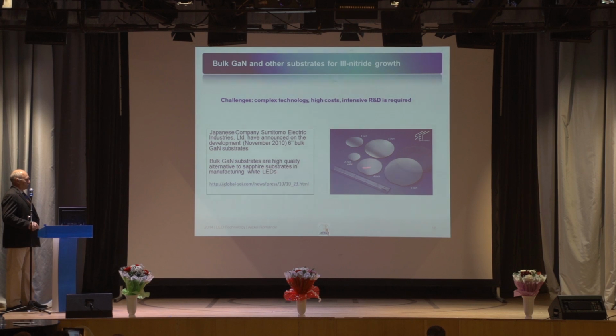And here, of course, there is a challenge to get such big wafers of gallium nitride. Gallium nitride is a material which does not grow at atmospheric pressure in liquid phase. So it can grow only at very high pressures from liquid phase. And therefore, such technologies which are usually used for silicon and other types of materials cannot be applied here. Therefore it is extremely difficult to get such wafers of gallium nitride to substitute sapphire wafers. And I can tell you that nowadays the price of maybe a 2-inch wafer is about $1,000 for gallium nitride, when you compare it with sapphire, where it is maybe $20 or less, you see the big difference in the price.